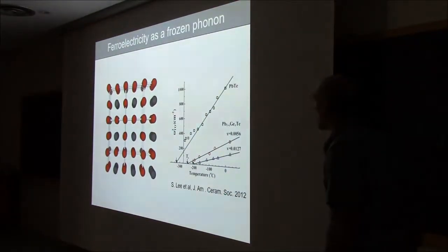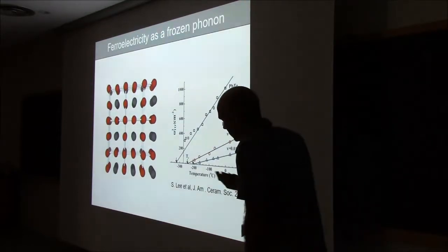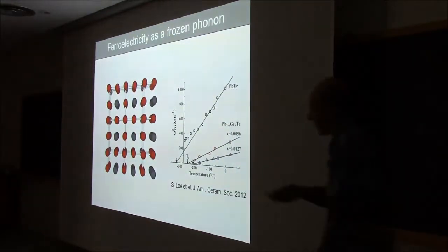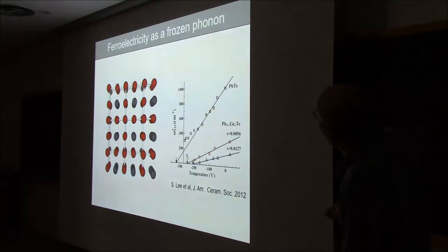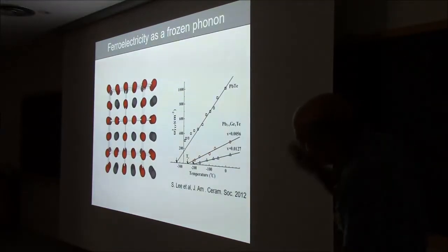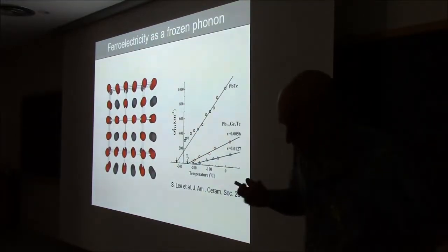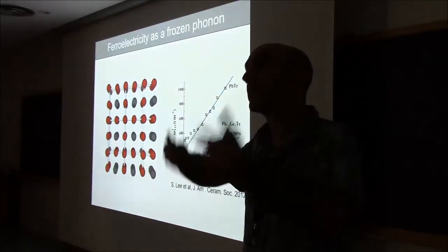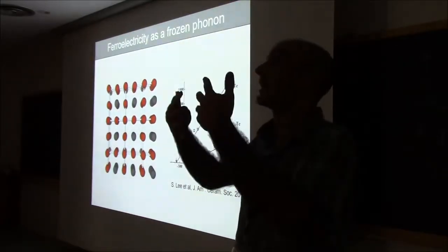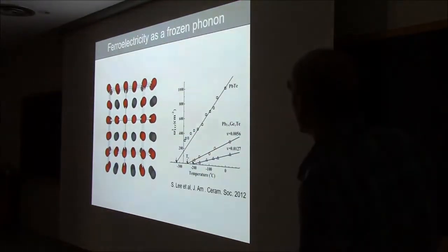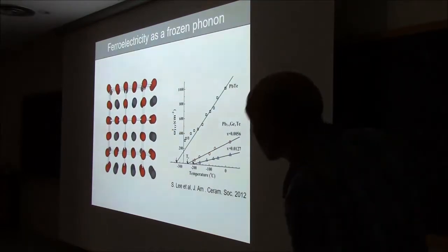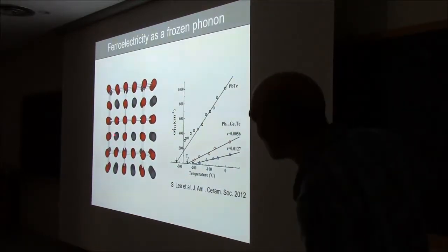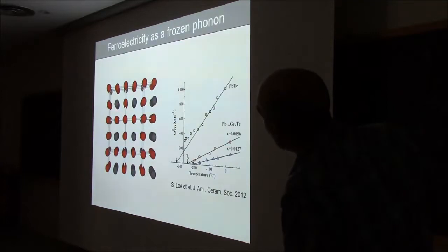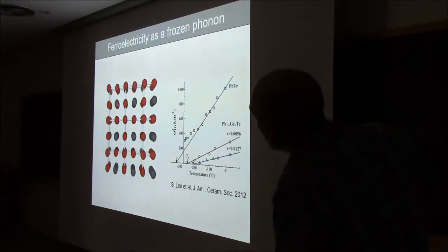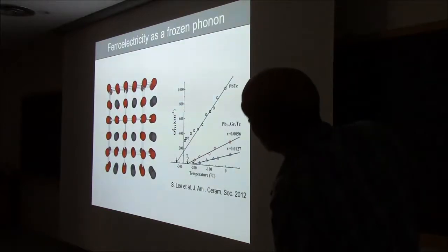From the point of view of, let's say, physics or solid-state physics, or I don't know what would be the point of view of this, you can think of ferroelectricity as a lattice vibration that is polar and that gets frozen, right? So this is a classic perovskite transverse optical phonon, and as you can see in these vibrations, the oxygen lattice is off-centering with respect to the cationic lattice.